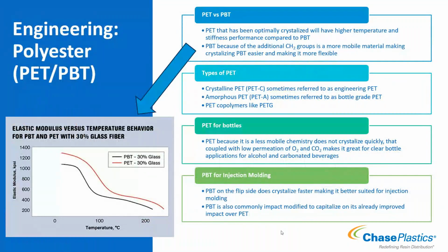Some performance differences: PET, once it's been optimally crystallized - so we take the time to make sure it crystallizes appropriately when we process it - PET can be a pain to crystallize, but if it meets its optimal amount, it will outperform PBT in temperature and stiffness. You can see in the graph, PET starts with a higher stiffness, maintains that, and doesn't start losing it until a little bit higher temperature than the PBT. So a little bit better stiffness and temperature performance if you optimize the crystallinity in your PET. But PBT, because of those additional CH2 groups, is more mobile - it moves a little easier, and it crystallizes easier and faster. Generally speaking, if you're going to injection mold PET grades, they're generally either filled or have some nucleating agent or filler to help aid in crystallization, because it does not want to crystallize very quickly when you're using PET.